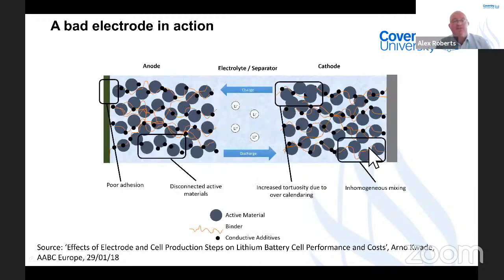So, to give an example of a very bad electrode in action, again taken from the same conference, we can see here what can go wrong. So we can have increased tortuosity if we calender too hard. We can block off parts of the electrode. We can have inhomogeneous mixing. You can see in the bottom right on the cathode, we have no conductive connections here.